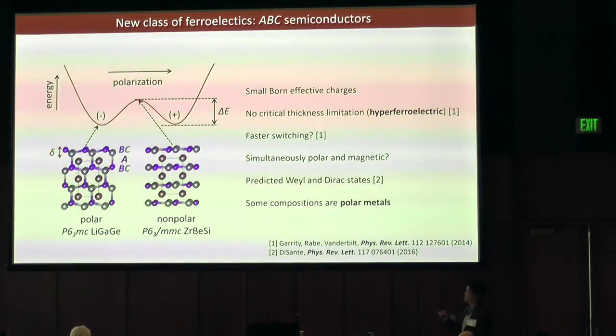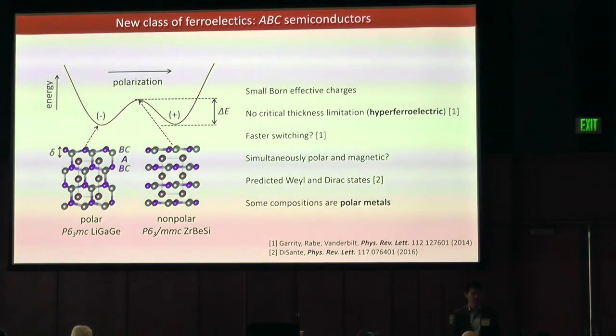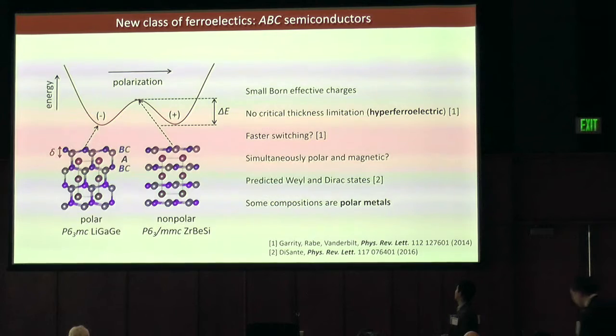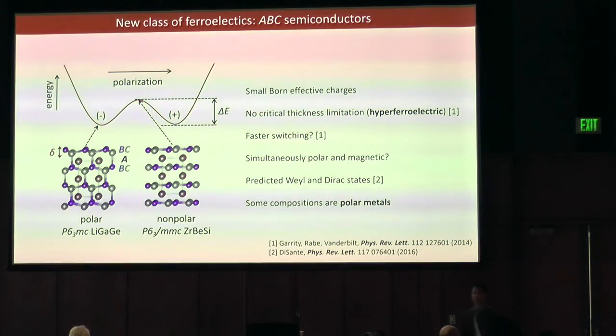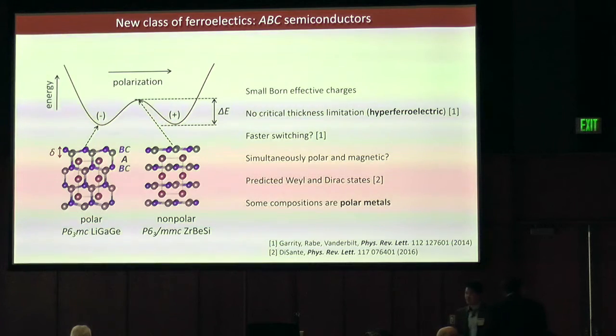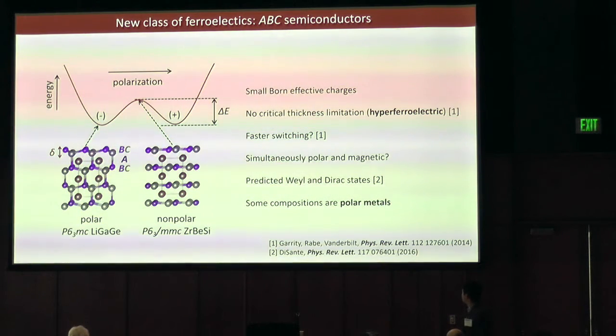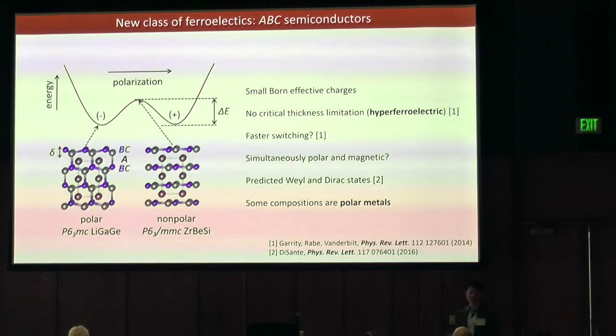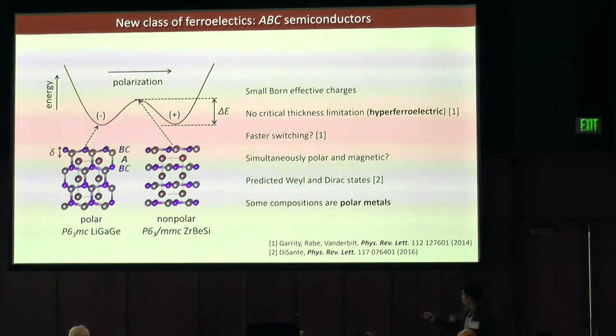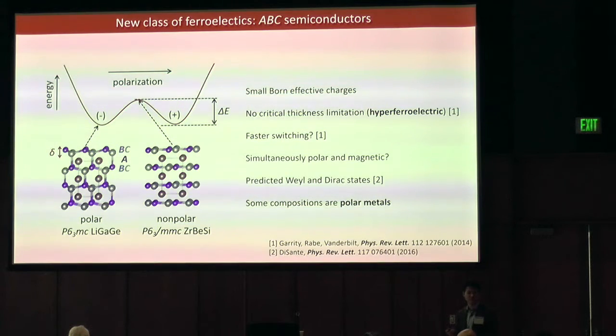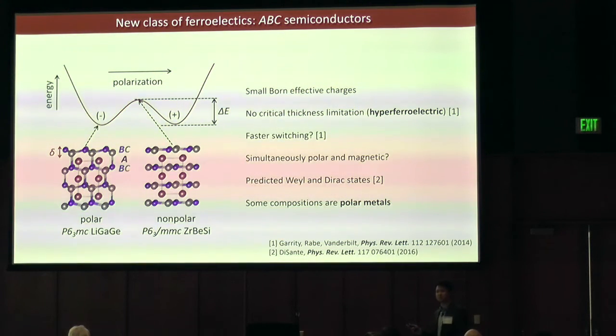So these have some interesting properties. These materials generally have smaller Born effective charges. They're much more covalent than ionic compared to perovskite oxides. Because of this hyperferroelectric property, there would be no critical thickness limit. Ideally, you'd have faster switching out of these sorts of compounds. Also, many of these compounds happen to be magnetic. A lot of them have rare earth cations at the A site. So perhaps this is another general class of materials in which to look for ferromagnetic ferroelectrics. And finally, a lot of these materials are actually natively metallic, and some are predicted to be Weyl and Dirac semimetals. So there's a lot one could look for in this particular class of materials.